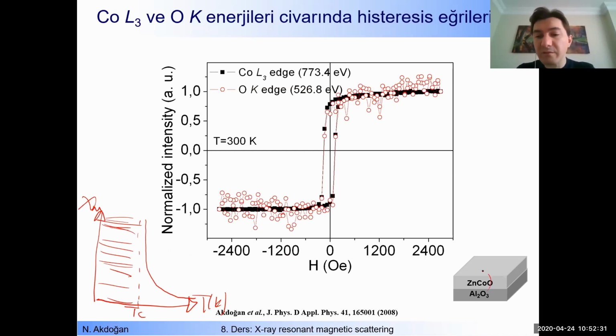For cobalt, this Curie temperature is huge. If you are talking about metallic cobalt, this Curie temperature is around 1400 Kelvin. We are talking about 300 Kelvin, so we are in that range for cobalt. But sometimes, of course, as you mentioned, low temperatures are required to investigate magnetic properties of other materials.